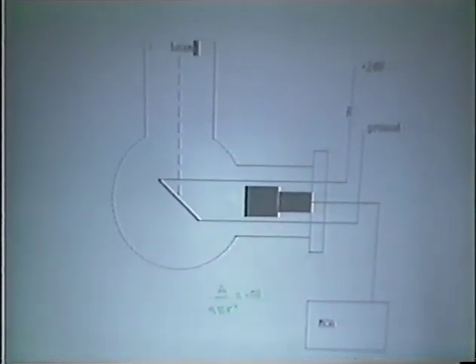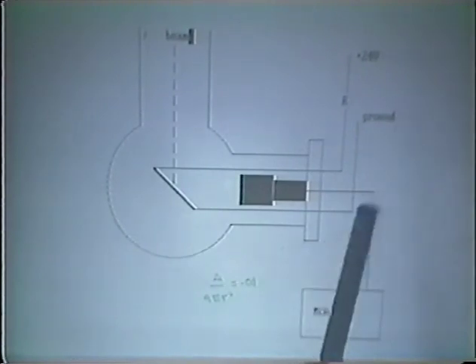The geometry of the experiment is indicated here. The beam from the accelerator hits a target which is at around 45 degrees to the beam. A 1 millimeter surface barrier detector, 3/4 inch diameter aperture, was located a few inches away, and in addition, the circuitry for running the current through the target was fed into the vacuum. The vacuum was around 2 × 10⁻⁷ torr. The surface barrier detector was used not only to look for reactions after the loading had taken place, but also to monitor the loading process.